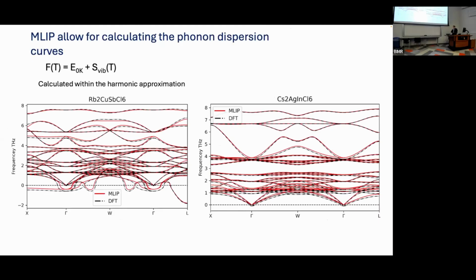It's not sufficient, as I showed earlier in my talk, there's a phase diagram that we also need to consider. So it's not sufficient to just calculate the stability of these materials at 0 Kelvin, but we have to understand how the energy might change as a function of temperature. So DFT gives us this 0 Kelvin term, but we have to calculate the entropic contribution to calculate the free energy. For solid state materials, one of the main terms in this entropic term is the vibrational entropy. To calculate the vibrations, we have diagrams like this, the phonon dispersion curves. So these are all the phonon bands. We have to calculate all the vibrations, the phonons, in order to calculate the free energy term.